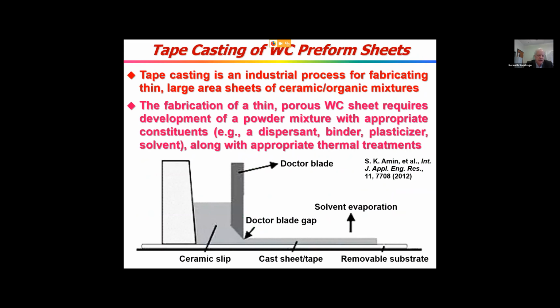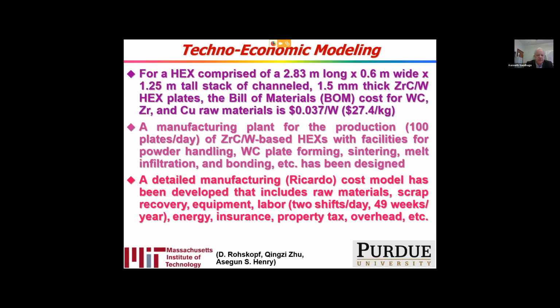So in terms of making large area thin sheets, a standard industrial way to do that, in the electronics industry in particular, is tape casting. You can make large area sheets of ceramic organic mixtures. Of course, to do that with tungsten carbide, we need a slip, a suspension comprised of the right dispersant, binder, plasticizer, and solvent. The idea is you pour that ceramic slip into a reservoir that flows underneath a gap under a doctor blade that defines the thickness of the tape, and the solvent evaporates off, and you can make, this way, very formable sheet. And so Asegun's group has done a really nice job of evaluating that in detail.